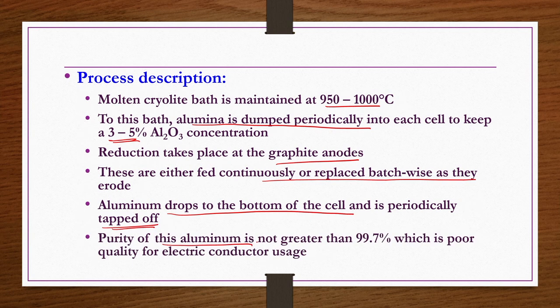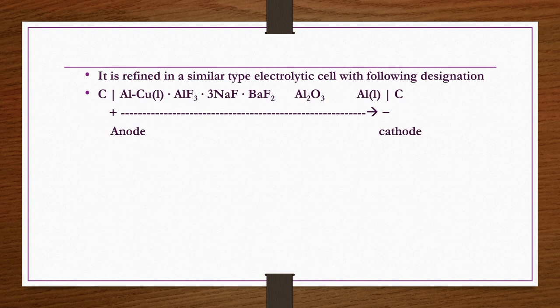The purity of this aluminum, however, is not greater than 99.7%, which is not good enough quality if you want to use this aluminum for electric conductor usage. So then it has to be purified to more than 99.9%. So how is it done? It is done in a similar electrolytic cell approach, in which at the anode, whatever aluminum copper alloy is there reacts with the graphite at the anode, and then it forms aluminum liquid, which is pure, and then that aluminum liquid passes towards the cathode. So, the process is the same, only the material is different here, okay?